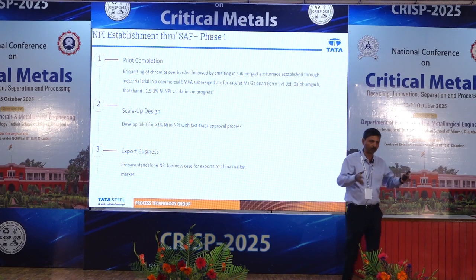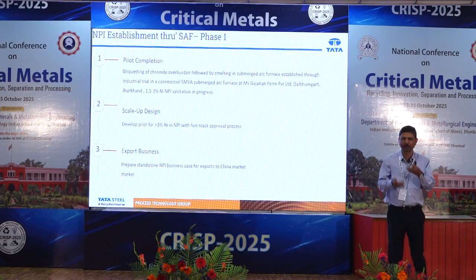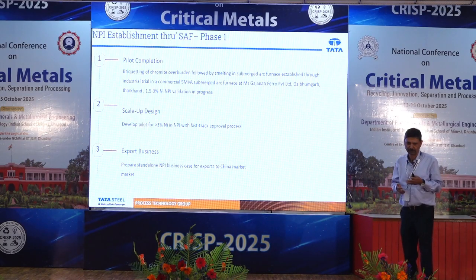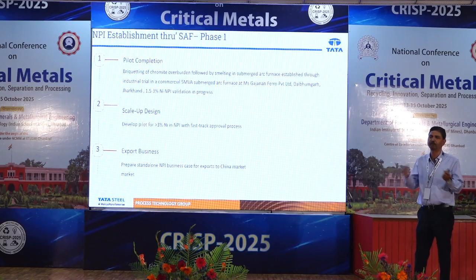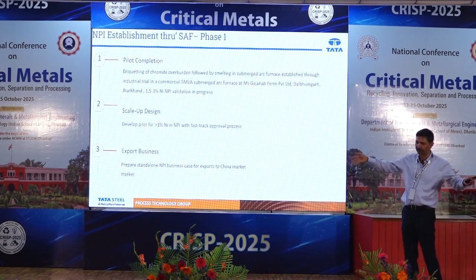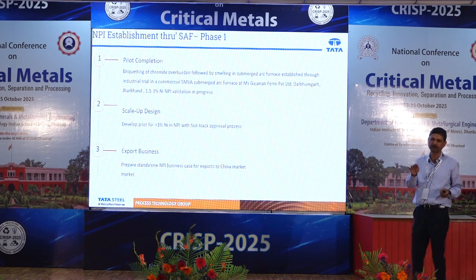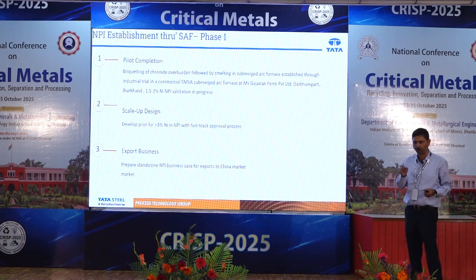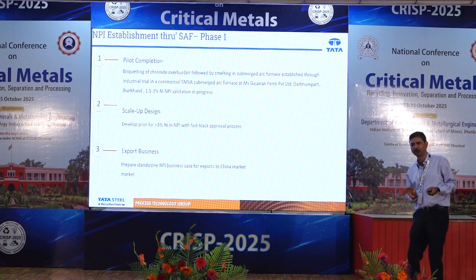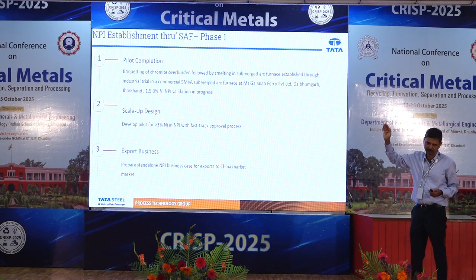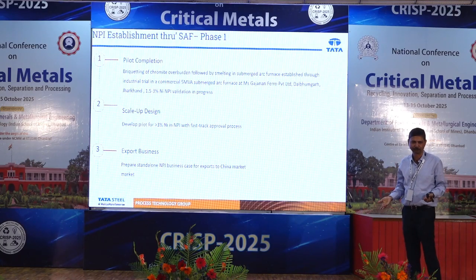The problem with Indian ore is that the ratio of nickel to iron is so poor. We are getting a maximum of 2% nickel. Basically we have 1 to 1.5% nickel. So on the reduction process, the maximum concentration can get up to 2 when you can manage the FeO movement towards the slag. Otherwise the ratio remains the same.